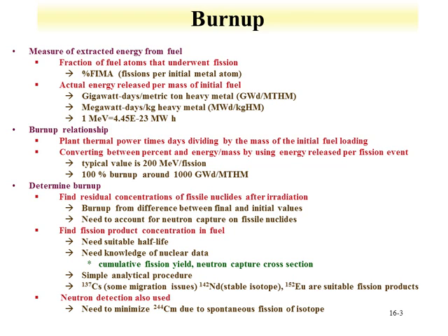This would have to have a half-life that would be relatively easy to measure, not too short, not too long. And you need to know something about its nuclear data. I would need to know its cumulative fission yield, so I know how much of that isotope is produced per fission, and its neutron capture cross-section, based upon the equation on the previous page, so we would know how much of that isotope had been converted to a heavier isotope as it was sitting in the fuel. There are certain isotopes, cesium-137, neodymium-142, and europium-152, that are often used as fission products to determine burnup.